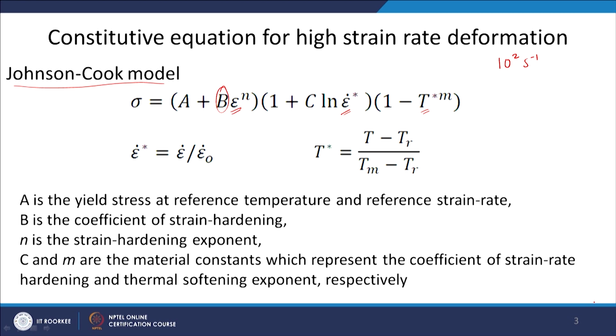One of the important ideas you should understand here is that when we do any high strain rate deformation, whether in hot working or, in this case, even higher strain rate, more than 10 to the power 2, there is always a temperature rise in the material. When we are deforming the material, we are inputting energy into the material. Some of the energy you are inputting goes into the deformation process, that means plastic deformation, and some energy goes in the form of heat.